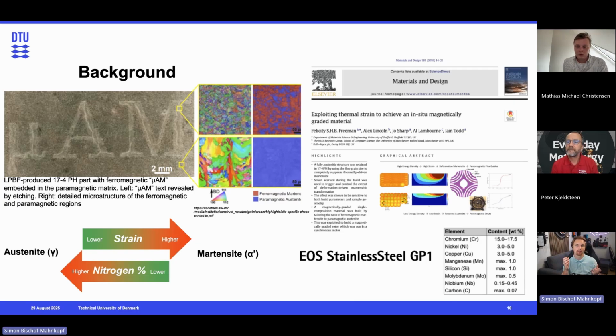So when making this powder, you normally have a big melt pool where you blast it with a gas to create these small powder particles. And when using nitrogen, you actually get a higher nitrogen content in the powder, which stabilizes the austenitic phase. This meant that we actually had a print that was austenitic even though it was a martensitic powder. And then we used the thermal strain to induce strain-induced martensite in the print. And therefore, by varying the thermal gradients during the cooling, we could actually get localized martensite formation and localized austenite, retained austenite.